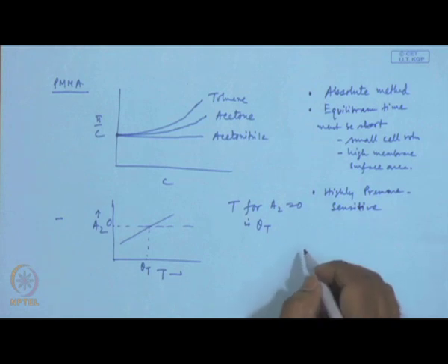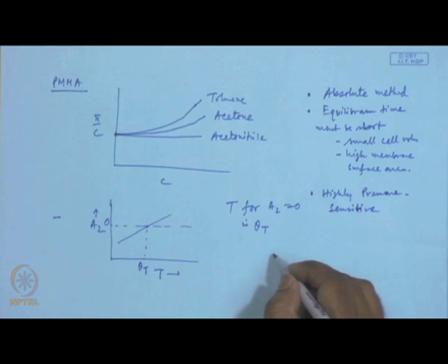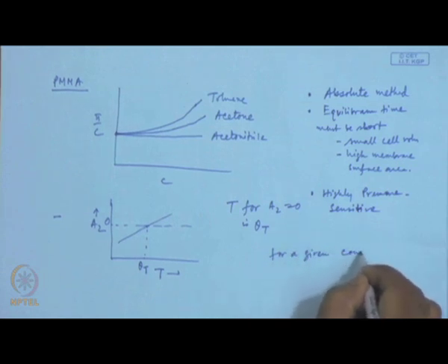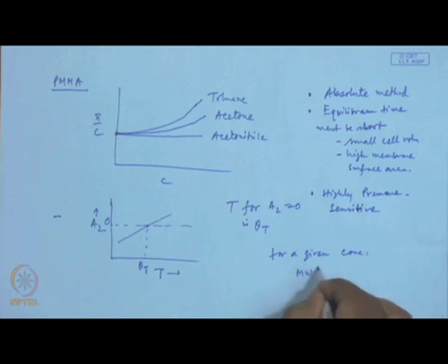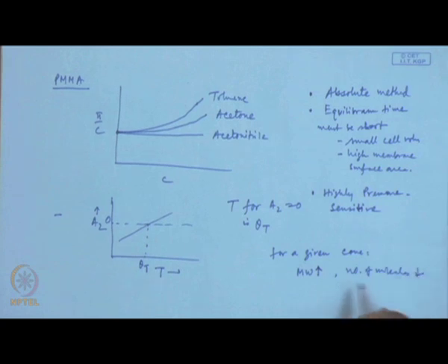As we can see, for a given concentration of solution, if we increase the molecular weight, the number of molecules goes down, and so does the osmotic pressure.